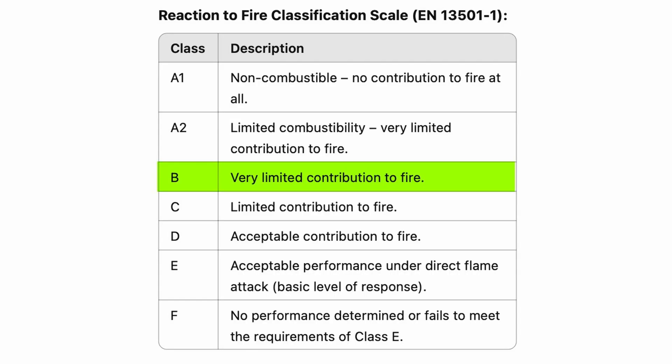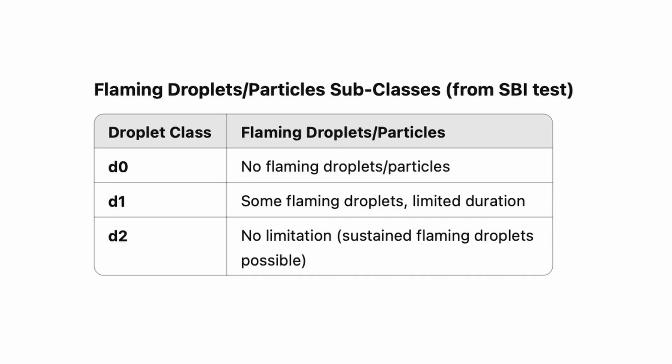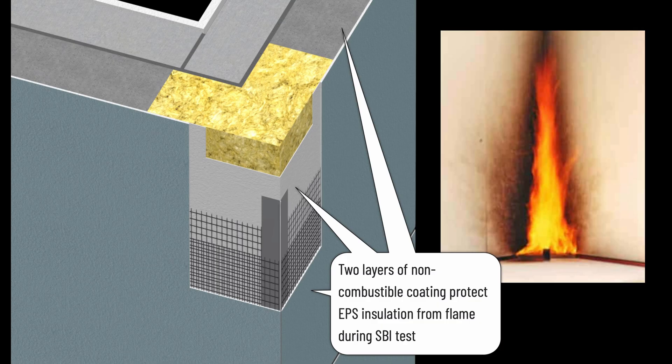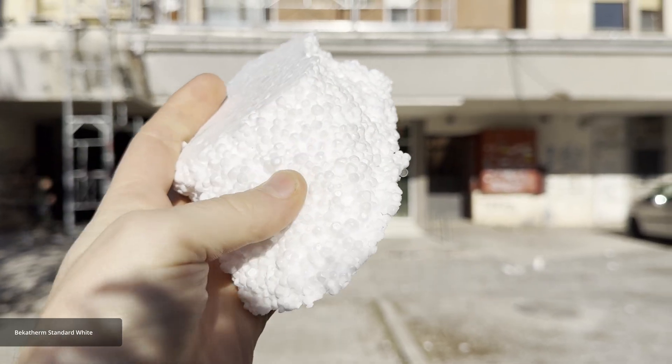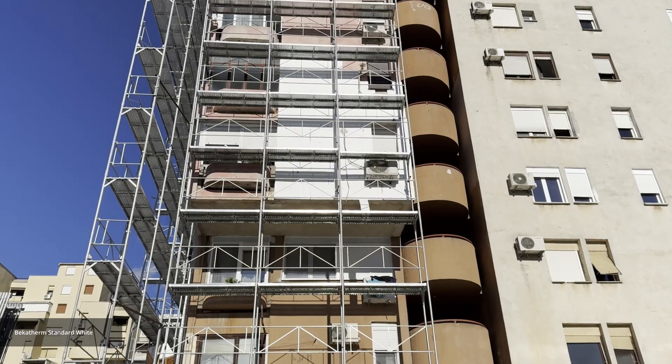The reason is that unlike individual materials, facade systems are classified for their reaction to fire according to a different test — one designed to emulate the reaction of a wall exposed to a small fire like a wastepaper basket in the corner of a room. This test monitors spread of flame from B (very limited) to A2 or A1 (limited combustibility or non-combustible), as well as emission of toxic smoke (S) and production of flaming droplets (D). In the case of a render system, EPS insulation is covered by two layers of cement-based coats which, if exposed to a lateral flame, do not allow the combustible polystyrene to ignite. This allows system manufacturers to classify EPS insulated render systems as B-rated, making them seemingly suitable for high-rise buildings under local building codes — and this is how these systems found their way onto mid- to high-rise buildings in Europe and around the world.